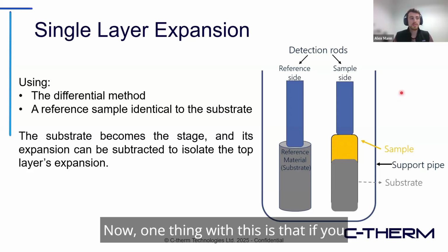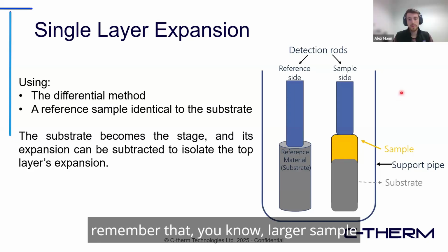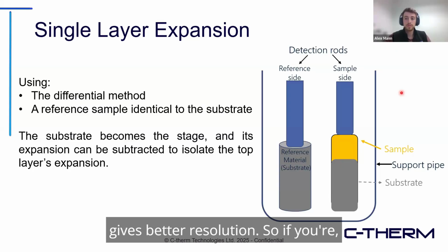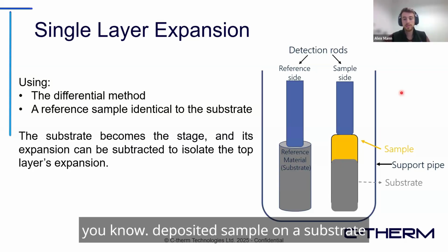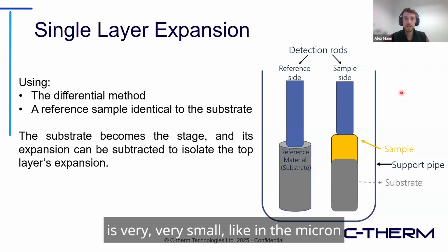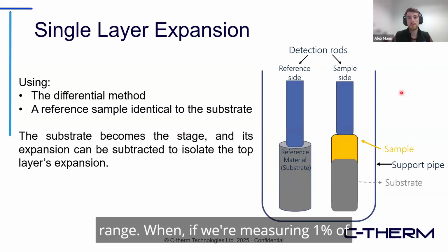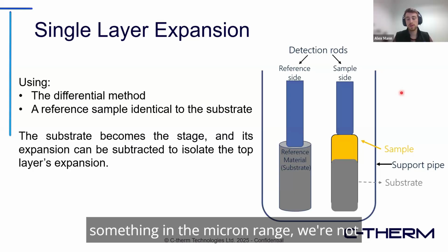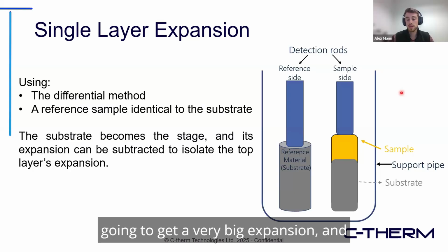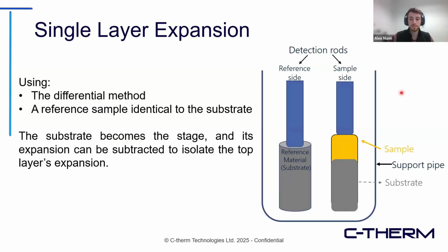Now, one thing with this is that if you remember, a larger sample gives better resolution. So if your deposited sample on a substrate is very, very small, like in the micron range, well, if we're measuring 1% of something in the micron range, we're not going to get a very big expansion, and you're not going to get very good resolution.